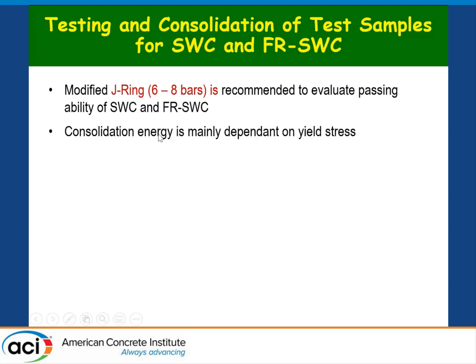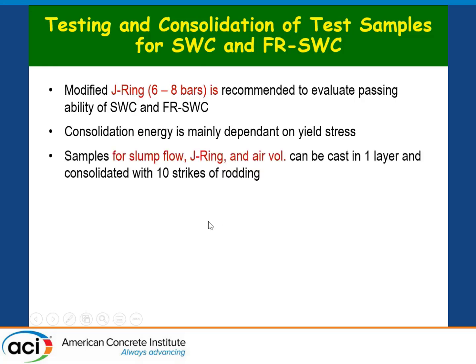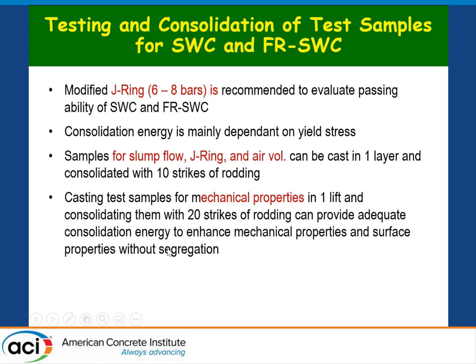The consolidation energy that is needed to consolidate and increase mechanical properties and density of super workable concrete and fiber reinforced super workable concrete is mainly dependent on yield stress or slump flow. When preparing samples to determine slump flow, J-Ring, air volume, we recommend casting the super workable concrete in one layer and striking it internally using 10 strikes using the rodding. And when we are preparing samples for mechanical properties, we recommend also casting them in one lift and then striking them 20 times.